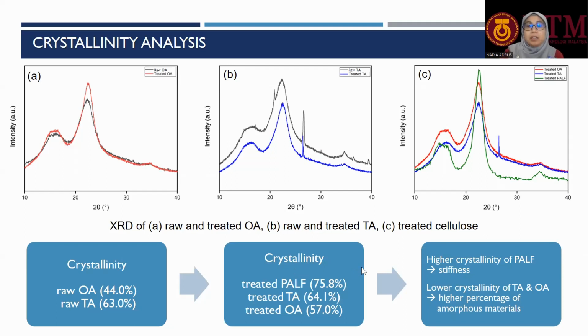From here, we can also deduce that the higher degree of crystallinity of PALF gives the stiffness properties of the pineapple fiber, and because of the lower crystallinity in TA and OA, this means they contain a higher percentage of amorphous materials, that means non-cellulosic parts in this fiber, compared to the cellulosic part.